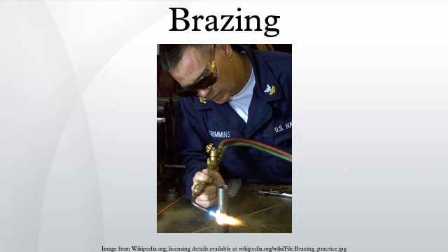Boron tends to diffuse into the base metals, especially along the grain boundaries, and may form brittle borides. Carbon can negatively influence some steels. Care has to be taken to avoid galvanic corrosion between the braze and the base metal, and especially between dissimilar base metals being brazed together. Formation of brittle intermetallic compounds on the alloy interface can cause joint failure. This is discussed more in depth with solders.